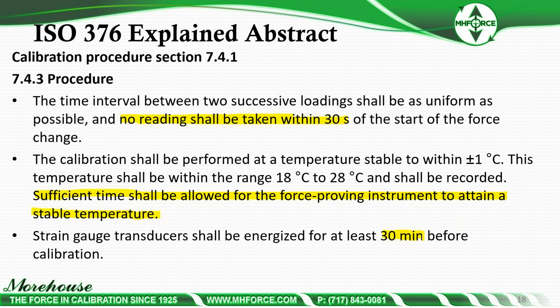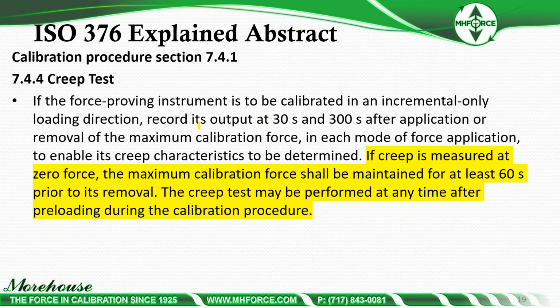Strain gauge transducers shall be energized for at least 30 minutes before calibration. This is good practice anyway to warm up the equipment, to get the signal, if you're using 5 volts, 10 volts excitation, to get everything warm and electrically stabilized. Creep test: if the force proving instrument is to be calibrated in incremental only loading direction, so if we're not doing reversibility, we're not doing the X4 and X6 calibration, six really sets of data, we're going to have to do a creep test.